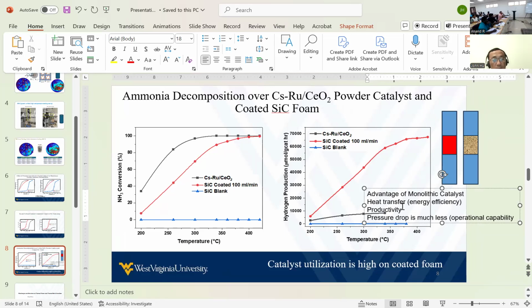I'm summarizing here. Heat transfer, and then because you heat it, the heat transfers from inside out. What does it mean? That means you heat silicon carbide, and then the silicon carbide heats the coated catalyst. So the heat transfer direction is from inside out. That means the moment the ammonia decomposes and the hydrogen comes out, it will never recombine with the nitrogen. So this is really the key to drive 100% conversion, because you take advantage of fast kinetics. Okay, I'm going to stop here.